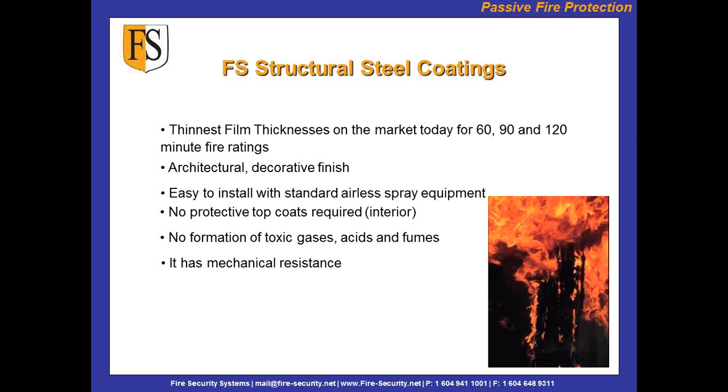And like we discussed about testing, if it's in full cure, it has extremely good mechanical resistance. If things are banging into it, like a truck or something, of course it's going to chip off, but then you can easily replace it because it's a homogeneous product. Once it's cured, you can come back and top over the coating itself in a damaged area, and it will cure to itself.